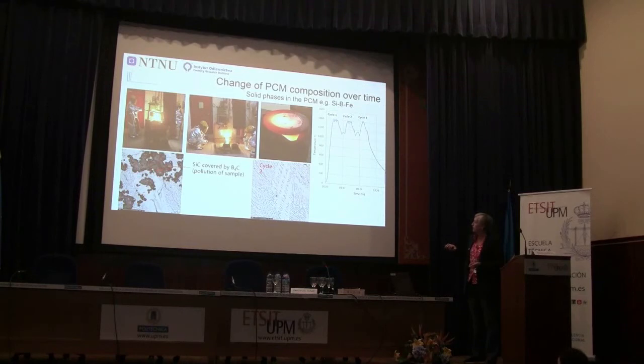The carbon will transform to silicon carbide. The boron in the alloy will react with carbon to boron carbide. So the light gray is silicon carbide, the black is boron carbide, and this will be solid all the time. Of course, it's not a go, no-go situation, but it will reduce the enthalpy change that you will have because you have more solid material in your alloy.